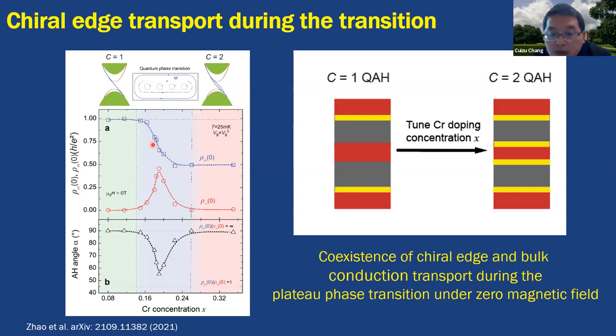But we know that in quantum Hall effects, there is also plateau phase transition. But that kind of plateau phase transition is usually driven by the magnetic field or by tuning the carrier density under high magnetic field. But here we can see that the plateau phase transition is realized under zero magnetic field. Actually, there is a very interesting phenomenon here. We can see that during the plateau phase transition, the ratio between the Hall resistance and the longitudinal resistance is always greater than one.